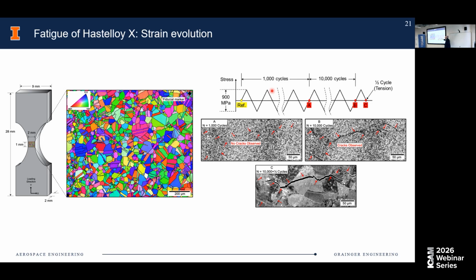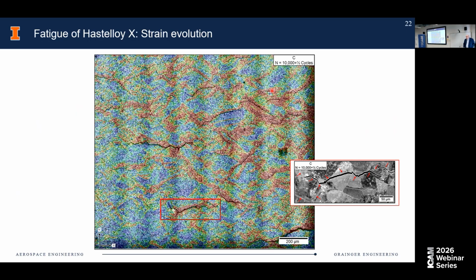This is an image at the point when the 10,000 cycles are concluded, and then sometimes we do another half cycle just to open up the cracks so we can look at them better. This is an optical image. This is an SEM image. And what we do is put the two together. So this is a superposition of the strain field measured at 1,000 cycles, before any cracking has appeared, and the cracks that appear at cycle 10,000.